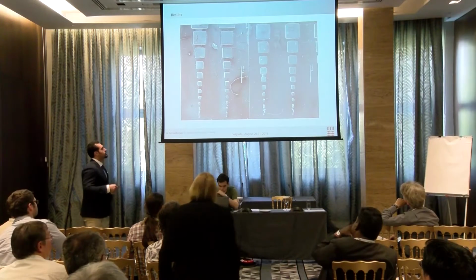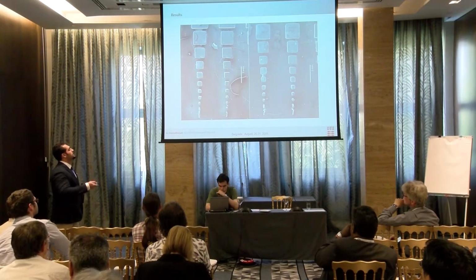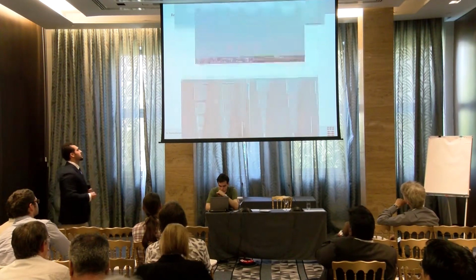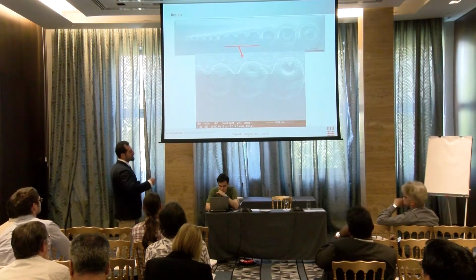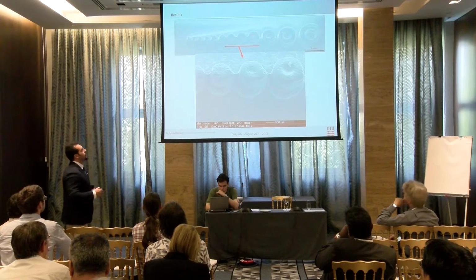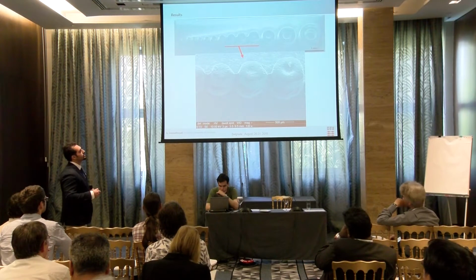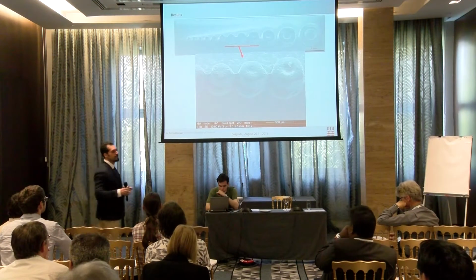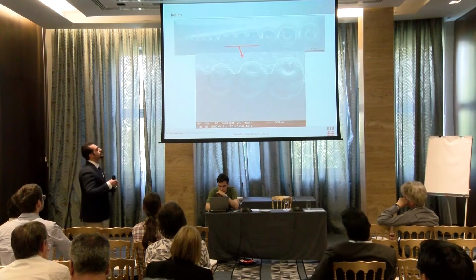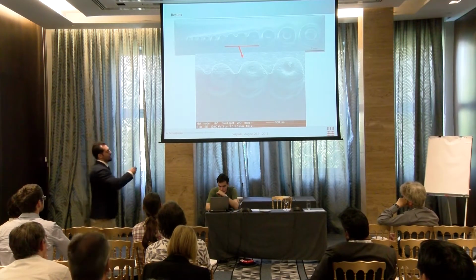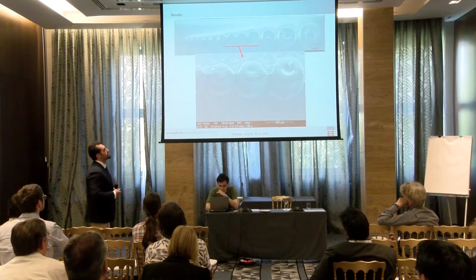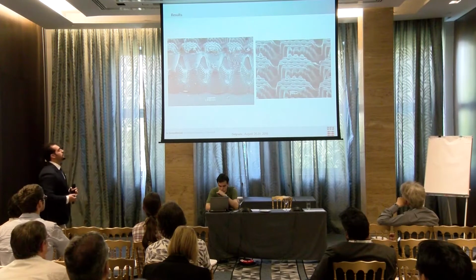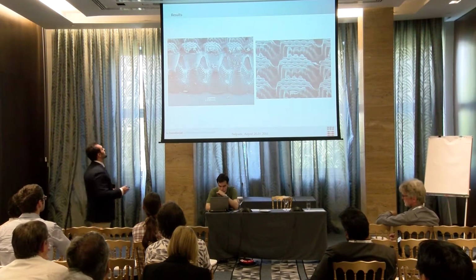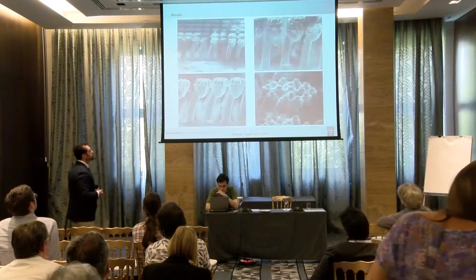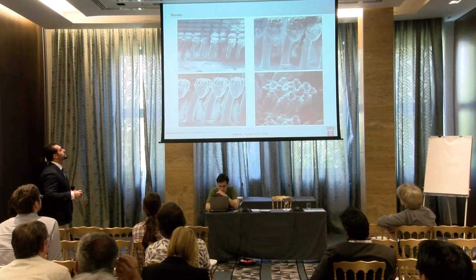This is some result with the poor post-processing. As you can see how it is affected, and the final part gives a poor result. The other effect of the post-processing is in the hollow component, and it's very difficult to remove the leftover resin from the component. Apart from the pixel size and the voxel that we have for the printing, mainly for the wall thickness, we also have this difficulty to remove the resin out of it. These are also some results with the poor post-processing, as you can see the resin is stuck there. And this is some result a bit better, and we managed to remove the leftover resin there.